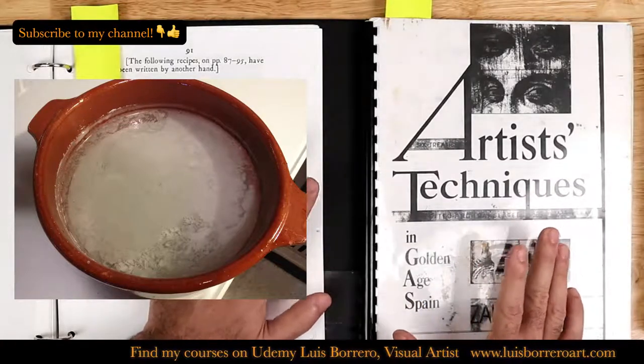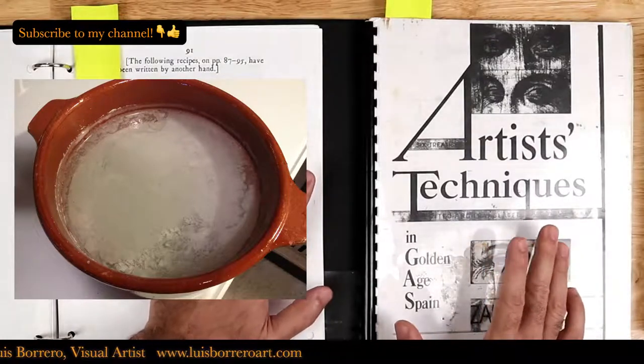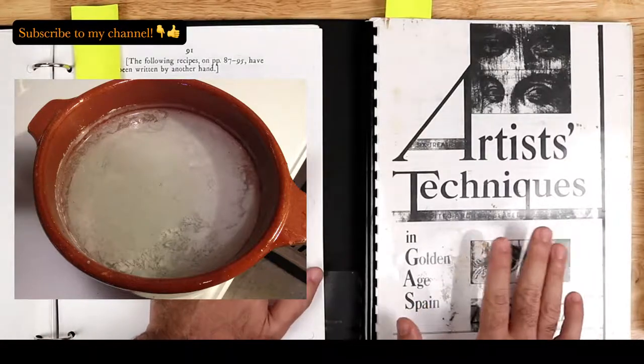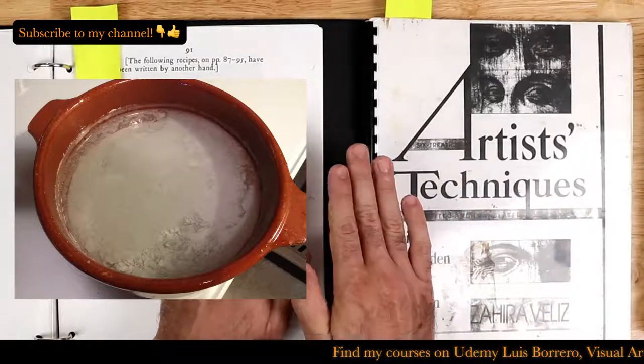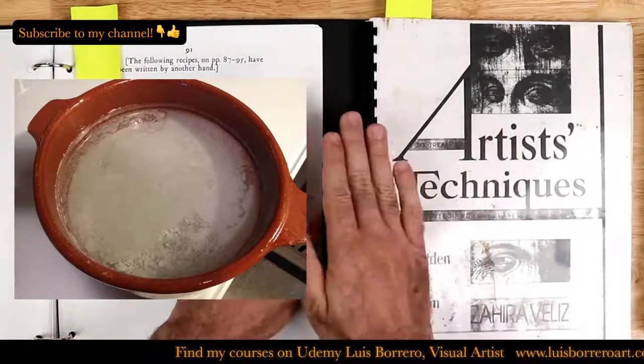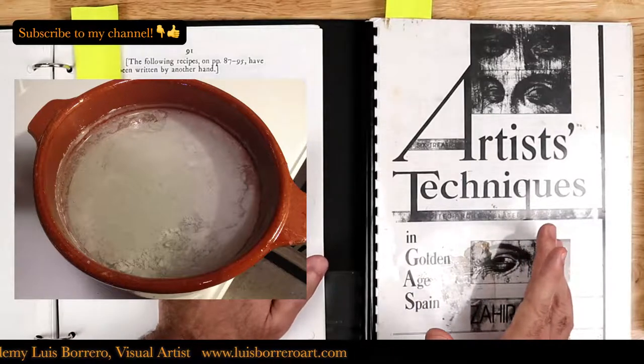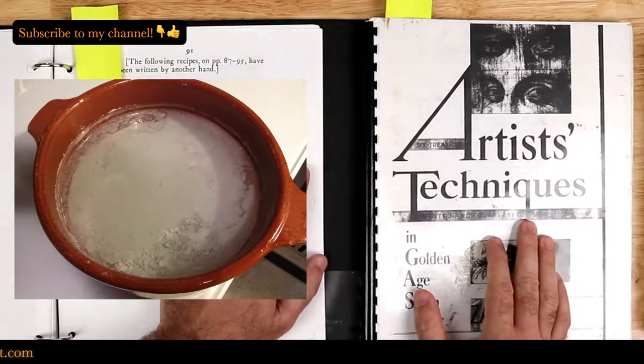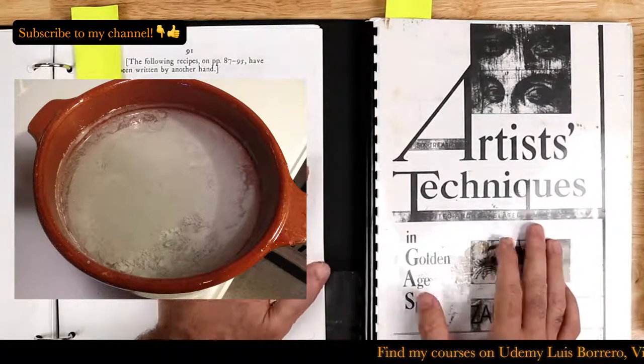I'm doing this with safety goggles, a respirator, and gloves, and I would never taste the water to make sure that the basic lead carbonate has been fully washed. What I do is use a pH meter and test the pH of the water, and if it tests neutral, it's essentially clean.